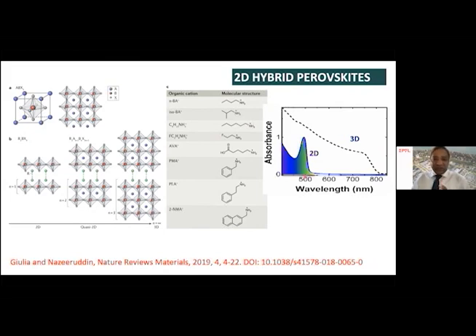This is not sufficient. What we want to do is combine the beautiful properties of the three-dimensional perovskite, which absorbs strongly in the whole visible region, but instability is significantly there. So we use a two-dimensional perovskite on top of the three-dimensional perovskite. The two-dimensional perovskites are very stable, but not absorbing in the whole visible region. Combining these two properties to get high efficiency and high stability. That's what you will see in my presentation.